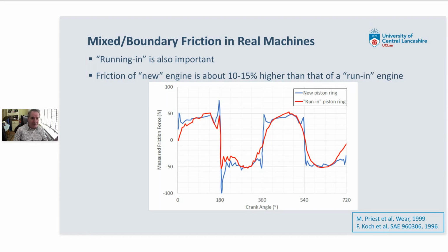Also, the component can actually change shape. This occurs for piston rings. The shape can change, and that can subtly alter the film thickness in the piston ring and give you thicker films. So you can end up with a worn ring giving you thicker films and having lower roughness, so that you get a double effect on the lambda ratio. For a new piston ring, you could get the lambda ratio being maybe 1, but after it's run in, it could be 3 or 4. So you can move from mixed and boundary through to fluid film. So that's showing what happens in real machines.